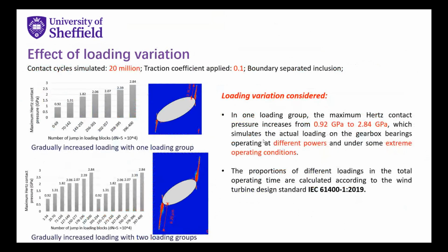In the end, I'm going to study the effect of the loading variation on the rolling contact fatigue. In this case, the loading is not a fixed value, but it changed from 0.92 to 2.84 gigapascal here. All these values come from the calculations of the wind turbine manufacturing standard.